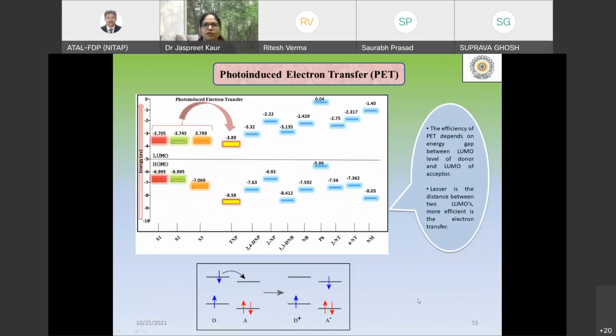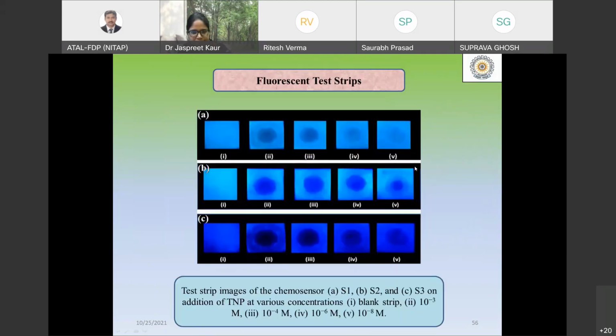So in these compounds we have the PET phenomenon. By finding out the HOMO-LUMO levels by CV, cyclic voltammetry, we found that the quenching has the PET, photo-induced electron transfer, phenomenon. You can see the energies of S1, S2, S3. These are the HOMO and the LUMO, and this is for the TNP. We have also prepared test strips of the organic compound and used them for the sensing of TNP at different concentrations. You see different concentration results over here. A is for S1, B is for S2, and C is for S3.